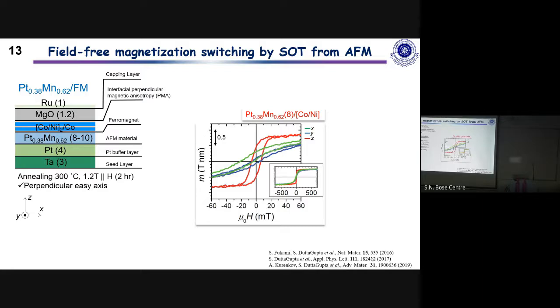How do you know whether this is ordered or disordered? The magnetic anisotropy you can measure from here. This is polycrystalline. Then how do you explain magnetocrystalline anisotropy, which is related to crystallographic direction? This is interfacial, perpendicular anisotropy. Interfacial perpendicular, but this is something at the interface here.